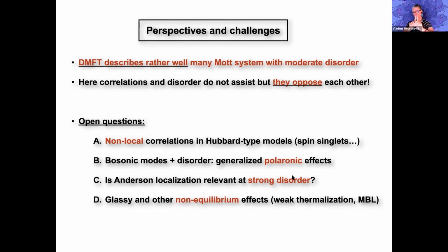When you bring them together in a dimerized fashion, it turns out that they start to form a strong singlet, and this effect can be captured in a DMFT fashion if you do a cluster calculation where you take basically a unit cell with 2 vanadium atoms, because once you have dimerization, your unit cell has 2 vanadium atoms. You may call it cluster DMFT, but you have 2 vanadium atoms in the unit cell.